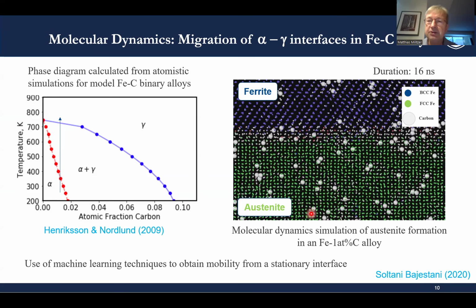So there's two observations here. For many of the steels that we are considering, the interface moves with carbon enrichment, and that's also confirmed with the atom probe tomography results, where we obviously see an enrichment of carbon at interfaces, including grain boundaries. And when we have just the transformation time here of 16 nanoseconds, even though carbon diffuses very quickly, it doesn't diffuse quick enough to have substantial diffusion distances in a few nanoseconds.